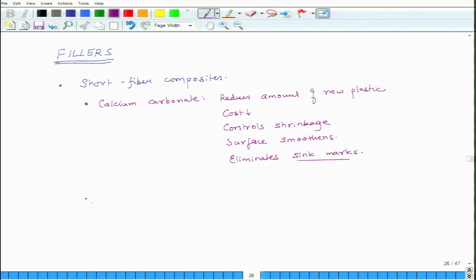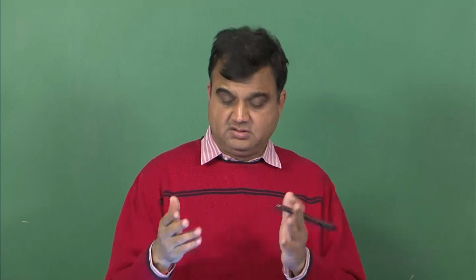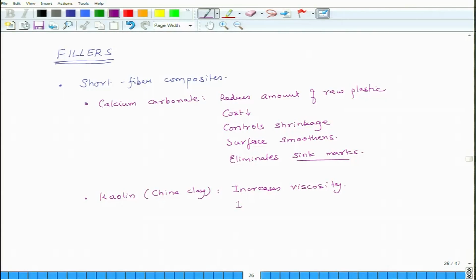Another filler is kaolin. It is also known as China clay. So, what does it do? If your resin is very thin, its viscosity is not high enough, then everything will not form the shape correctly easily. So, it increases viscosity. It all depends on what is your application. Okay. If the viscosity is not too high, if you inject it with fibers, the fibers may pop out of the surface, but if viscosity is high, they will not come out of the surface. Okay. So, that is there, and it also increases fire resistance.